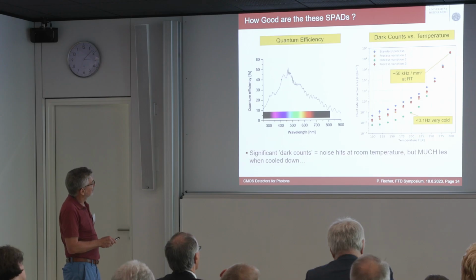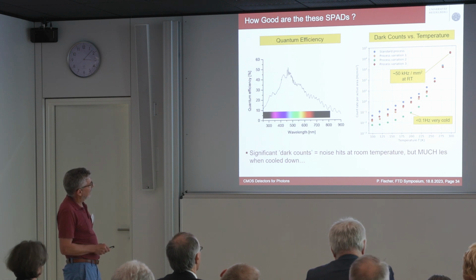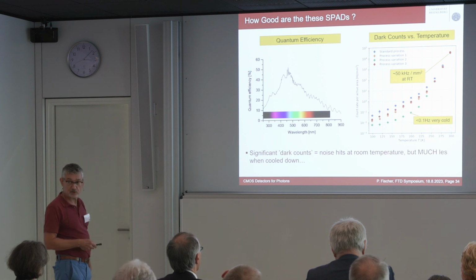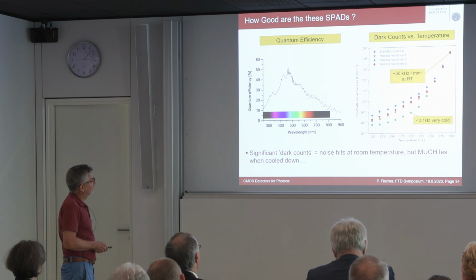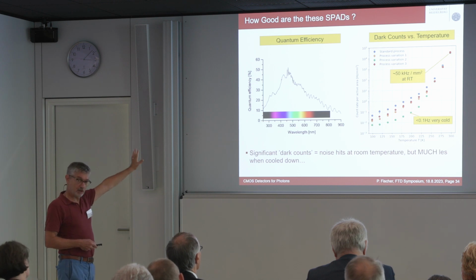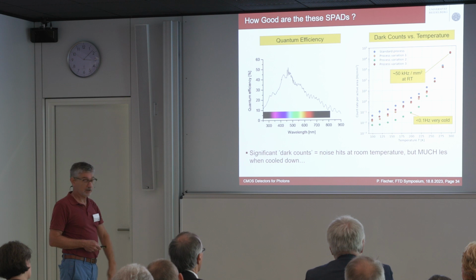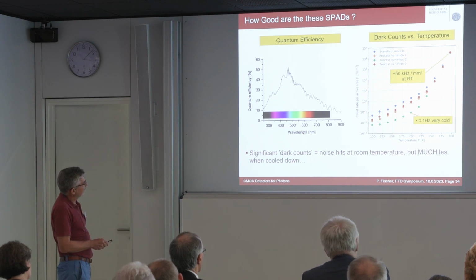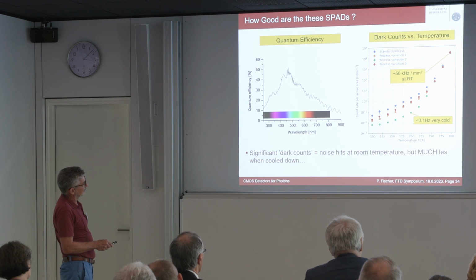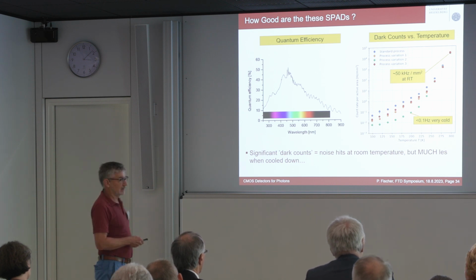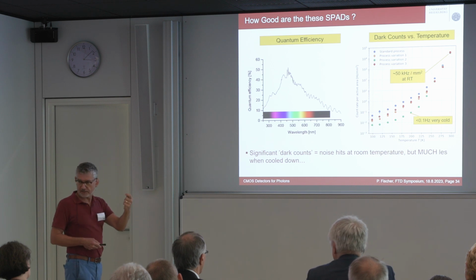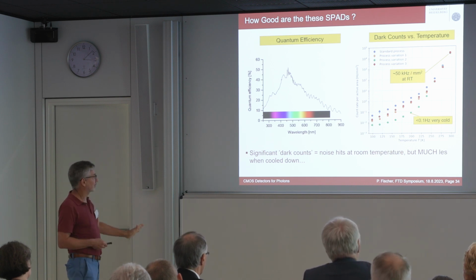But the good news is, if you cool it down, because the thermal excitation of electrons goes down rapidly, the dark count rates go down really a lot. And some of the applications we are investigating are at really cold temperatures, at liquid nitrogen or liquid xenon or liquid argon temperature. The devices still operate nicely. You can just dip them in liquid nitrogen. They just work. And you get dark count rates really close to, I'm conservative, less than 0.1 hertz. So one click every 10 seconds on a square millimeter device. So you really go down hard.